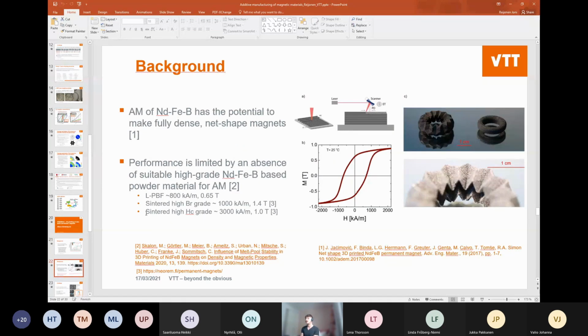Here is the earliest work, which was not done by us. This was by another research group. The results were published in 2017 about the first case of using laser powder bed fusion to process neodymium iron boron fully dense, so without a polymer bond, and to get some meaningful properties out of it. So a coercivity of roughly 800 kiloamperes per meter and 0.655 Teslas roughly for the remanence magnetization. These are quite good, but still they are not at the level of the high-end sintered magnets that you can make conventionally. Here I have some properties for two different grades, whether you want high coercivity or high remanence, because at some point it's a compromise again. You cannot have both in the same.